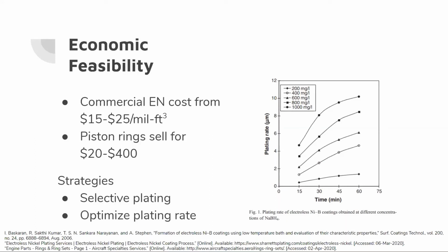The second option is to optimize the plating rate. If we look at this chart on the right, we can see that by adjusting the concentration of the sodium borohydride, or the reducing agent in the bath, we can actually increase the plating rate. So if we make sure that the concentration is 1,000 milligrams per liter, we can see that regardless of the time, we're able to increase the plating rate, which decreases the time required for manufacturing of this ring.